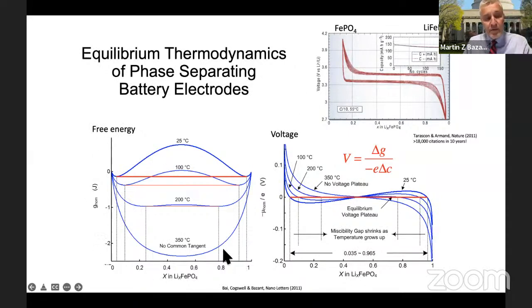If you've studied thermodynamics, you can imagine that if we look at the free energy of the system as a function of composition on the horizontal axis, then you may be in a situation where, especially at low temperature, you have a double well potential. What that means is that there are two special concentrations that are the lowest energy of the system if it remains homogeneous, meaning uniform concentration. But if you imagine starting at 0 lithium and adding lithium to the system, first you go down in energy, but then you start to go up. And in this region in between the two minima, which are connected by a so-called common tangent construction, it is thermodynamically favorable to take, for example, a 50% concentration system and drop down from the blue curve to the red line, which corresponds to a 50-50 mixture of each of the two stable phases.